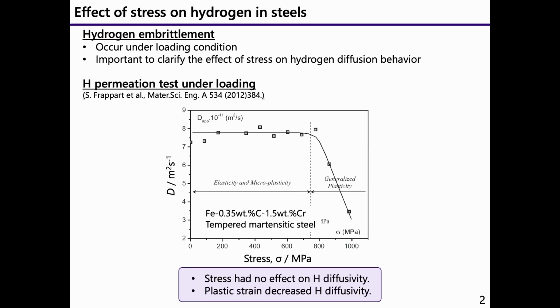Previously, hydrogen permeation tests were conducted under loading condition. For example, Frappart et al. reported the relationship between the diffusion coefficient and stress as shown here in tempered martensitic steel. In the region of elasticity and microplasticity region, the hydrogen diffusivity is constant. On the other hand, hydrogen diffusivity decreases in generalized plasticity region. Therefore, it has long been believed that stress has no effect on hydrogen diffusivity and plastic strain decreases hydrogen diffusivity.